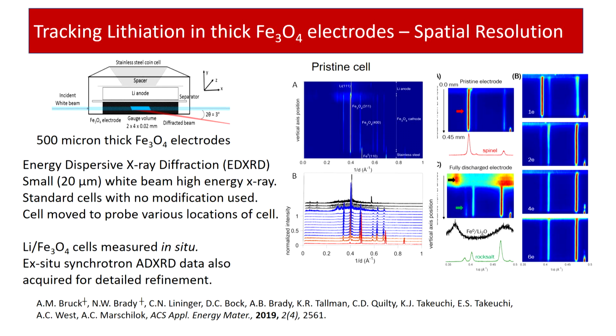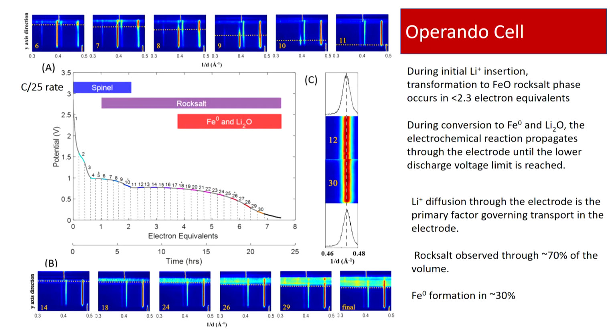And in this case, one can see that the full reduction of iron metal is shown in the middle here. The full reduction does not penetrate the entire electrode. We go on to do an operando experiment. So we're discharging this battery and measuring the ED-XRD through the cross-section of the electrode continually. And we can then find out that this reaction is in fact limited by lithium-ion access. The reaction that goes to completion is at the electrolyte interface. So this clearly tells us that kinetically, in order to utilize this electrode, we need to redesign the electrode to be able to capture more than 30% of the full realization of iron.